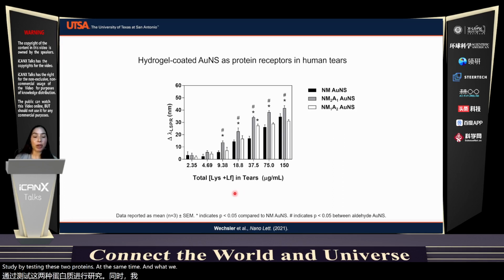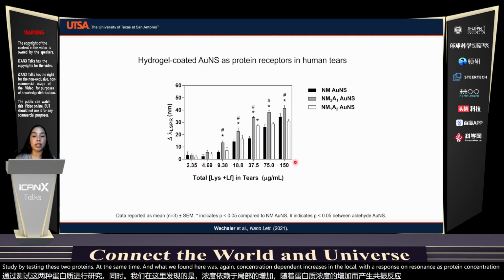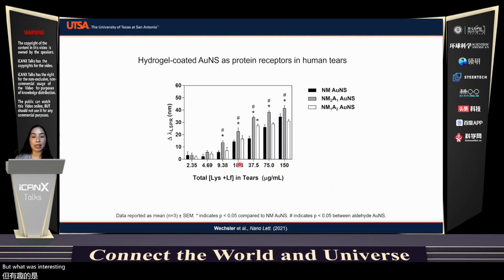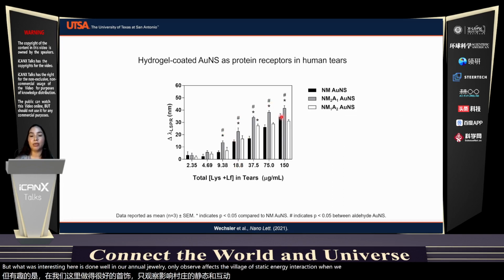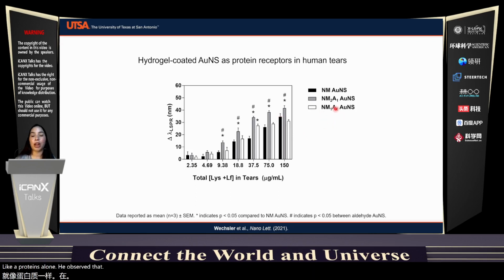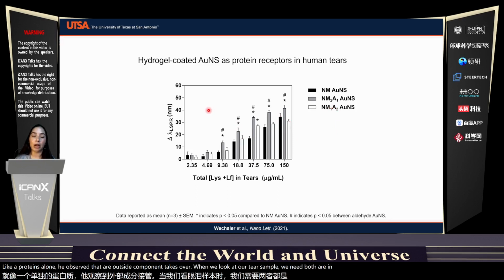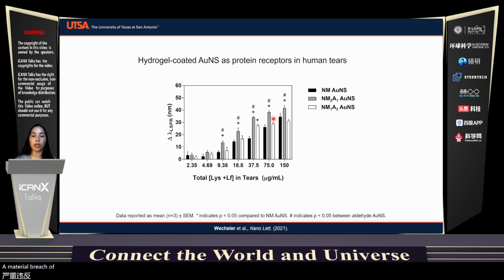And what we found here was, again, concentration dependent increases in the localized surface plasmon resonance as protein concentration increases. But what was interesting here is that while in our nanogel, we only observed effects of electrostatic interaction, when we add our gold nanoshells and looked at proteins alone, we observed that our aldehyde component takes over. But when we look at our tear sample, we need both our anionic material, but also the covalent monomer.